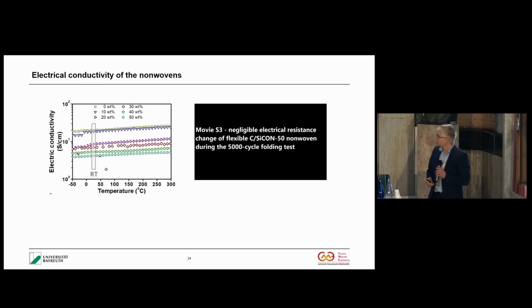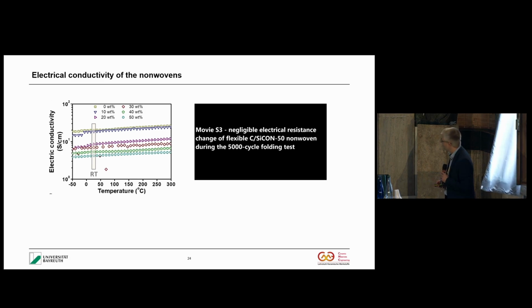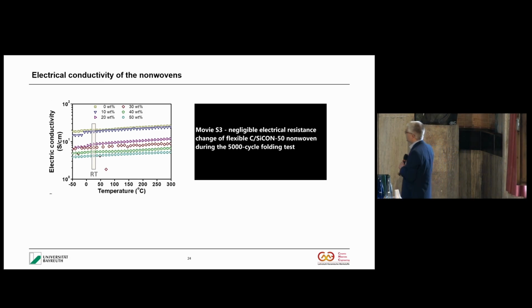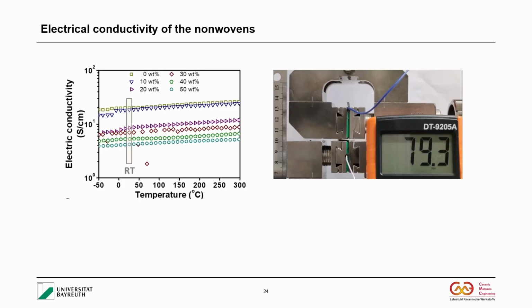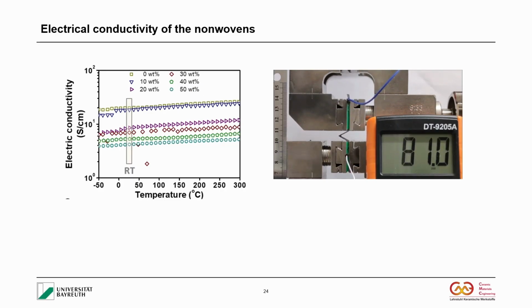And what is then interesting, due to the amorphous carbon, you also have a good electrical conductivity, which is quite stable even over a large temperature range. And this also means the electrical resistance is quite low. And if you click, please, on the next video, you see again the foldability. It does not change even after a lot of cycles.